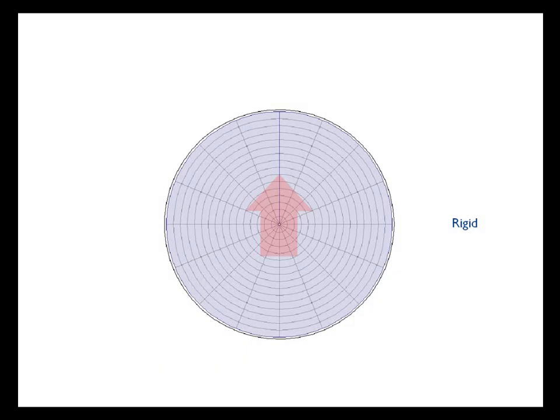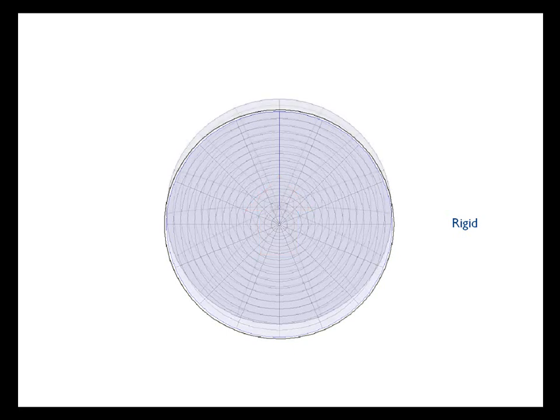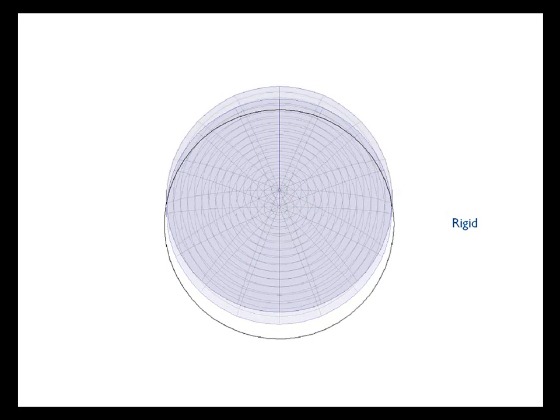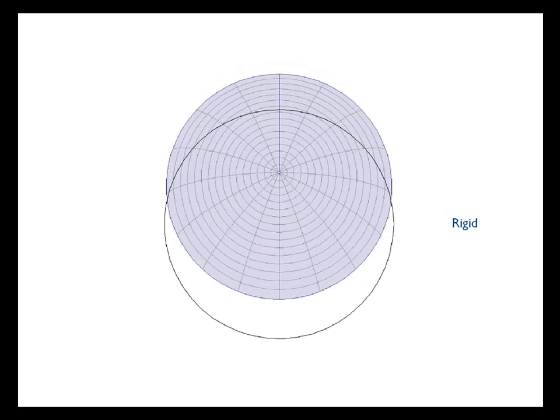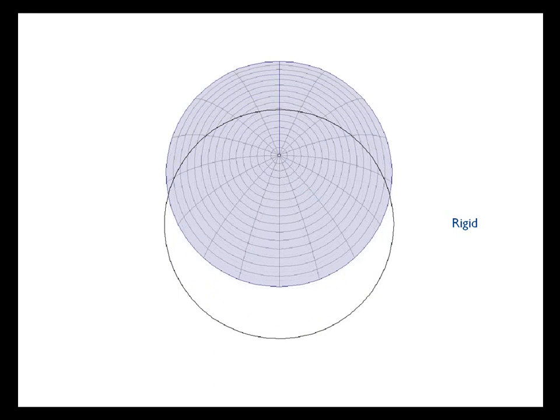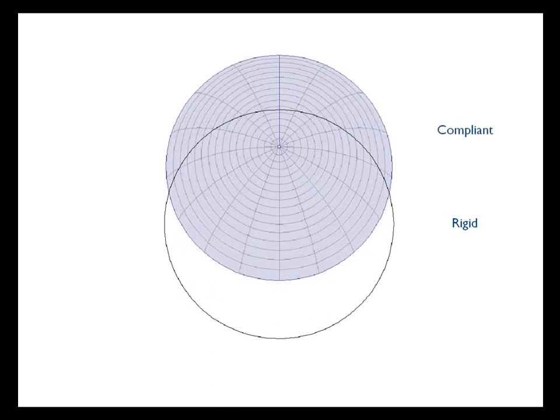Numerical calculations let us predict the deformation of an individual circular area, representing the adhesion site, for substrates of any stiffness. Not surprisingly, the site is motionless for very stiff substrates. After all, a cell can hardly deform glass, whose stiffness is 70 gigapascals, or polystyrene, about 1 gigapascal. But a cell can more easily deform hydrogels, whose stiffness can be in the kilopascals, as compliant as cells themselves, and 1,000 times more compliant than soft rubber. Let's look more closely at this deformation.